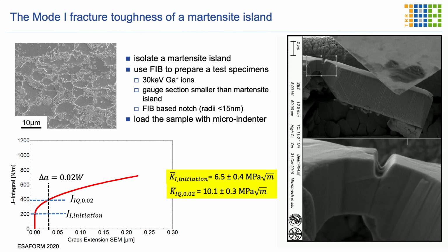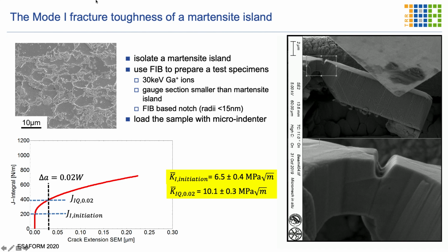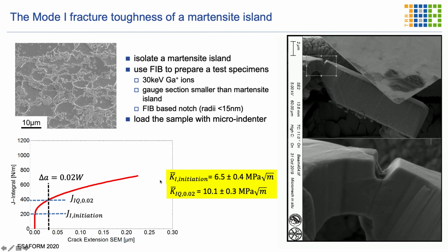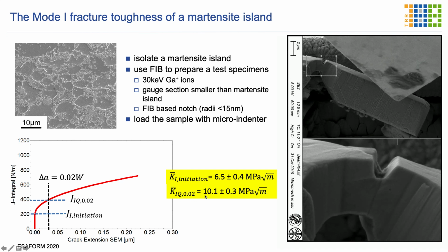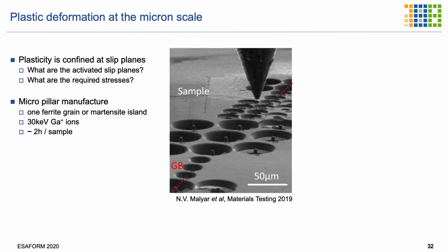Now, this is an average one because depending on the composition of the martensite, you get different values, and what we determined here is for the batch of different values, an average initiation stress intensity factor, and a stress intensity factor of a strain of 0.02. So this is a very fundamental research which we can use directly in our models.